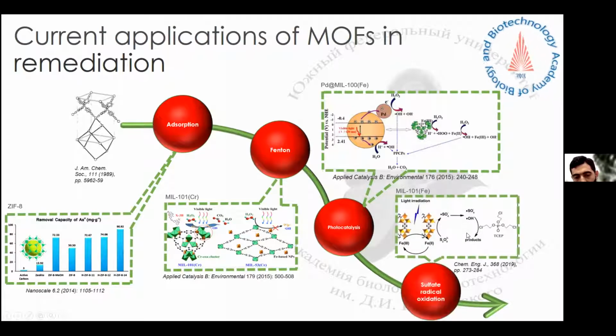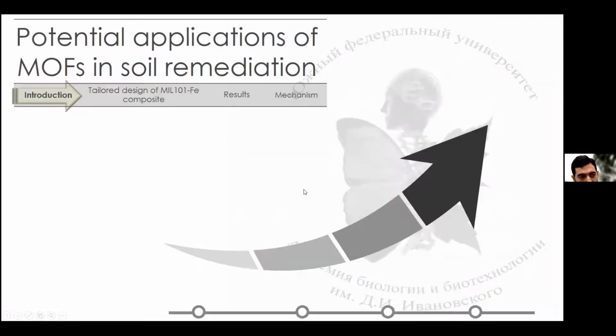And the last one, which has been a subject of a lot of different metal-organic framework structures, is sulfate radical oxidation, where we have a persulfate and we have to activate it with different catalytic metal-organic frameworks. One of them, again an example of MIL-101 based on iron, can activate persulfate and produce a sulfate radical, then target the organic contamination. So the future is still going on, and I believe that a lot of aspects still need to be addressed by many researchers.